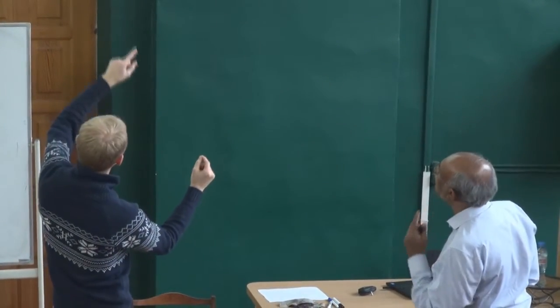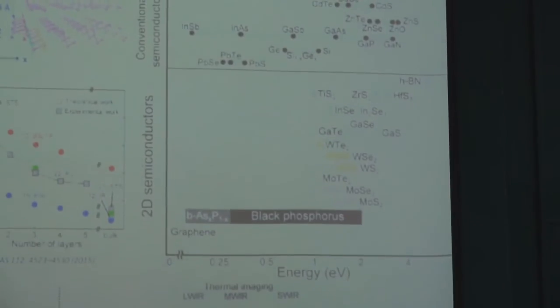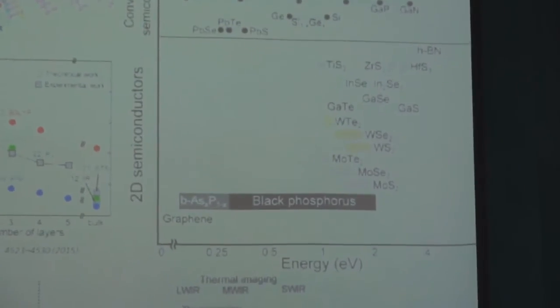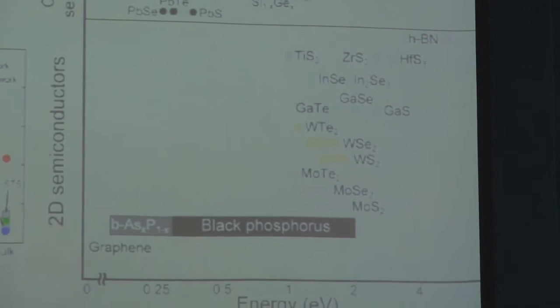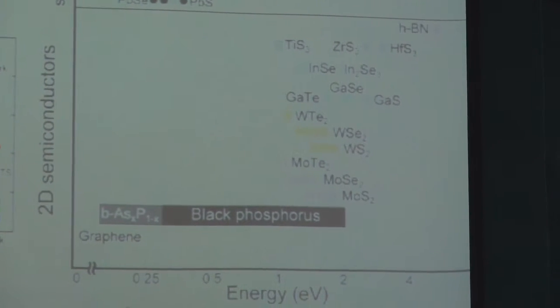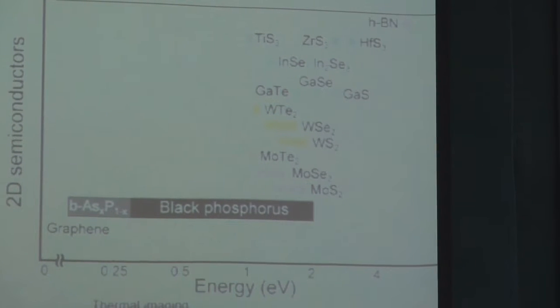We have step change or tuning of the band gap. Yeah, depending on the number of layers. If you start with bulk black phosphorus, you have a band gap of only 0.3 electron volt. But if you go to 1 layer, it's about 2 electron volt. That's a big range, right?